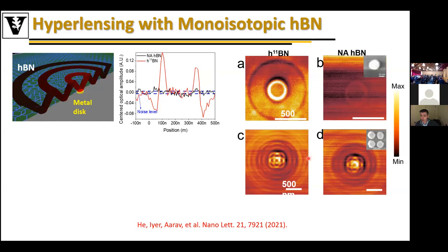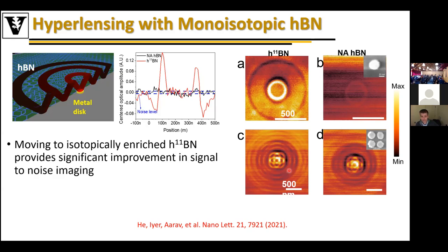Plus, if I look at more complicated structures, for instance, this 2x2 array of 100 nanometer particles with a 25 nanometer gap, I can actually get a much cleaner image of the field pattern that could allow me to then better identify the structure underneath. And if we compare the signal noise level between the natural abundant in black and that of the boron nitride for these structures, you can see a significant improvement, implying that we could actually even get smaller than the structures